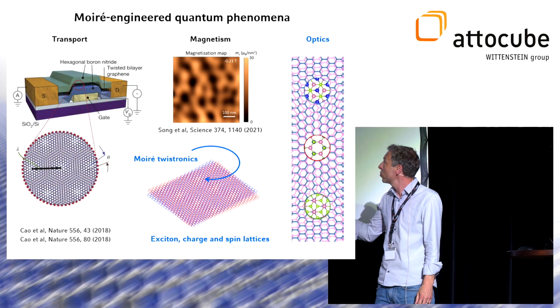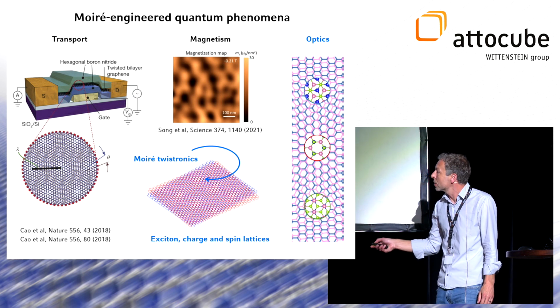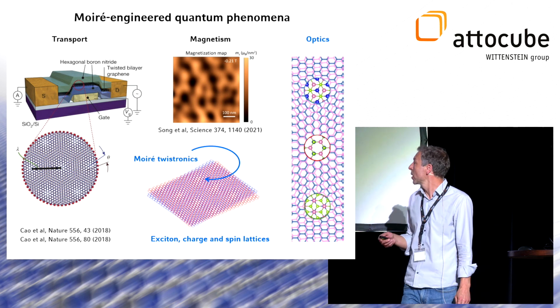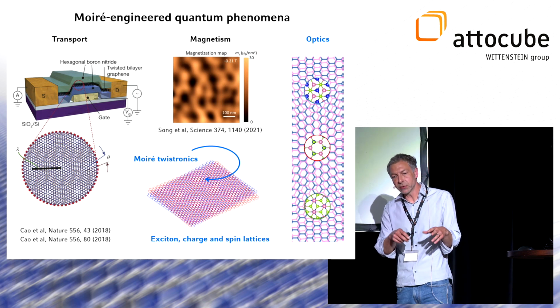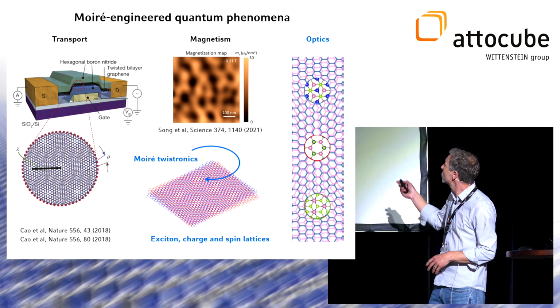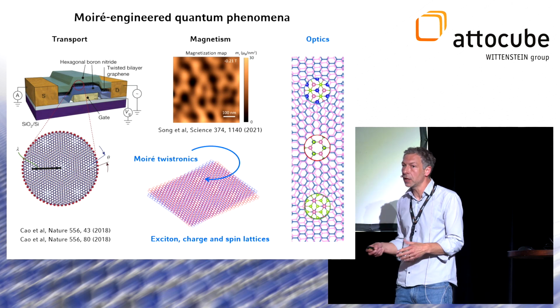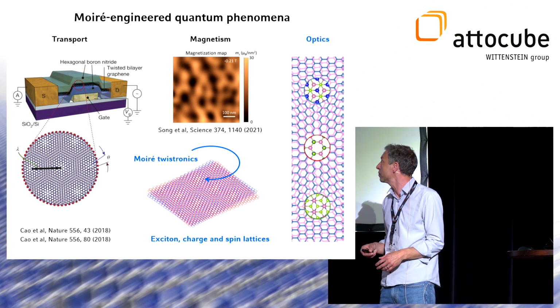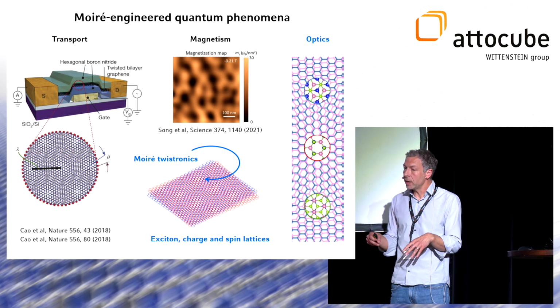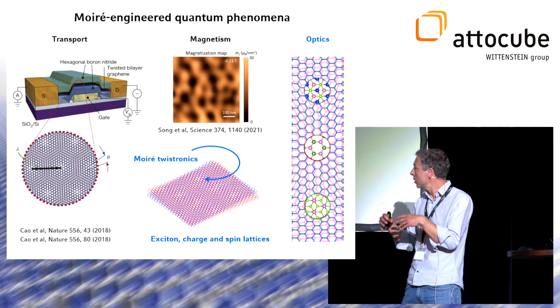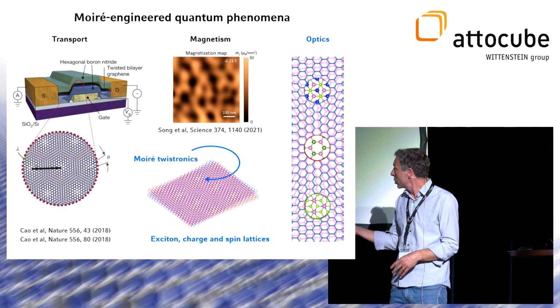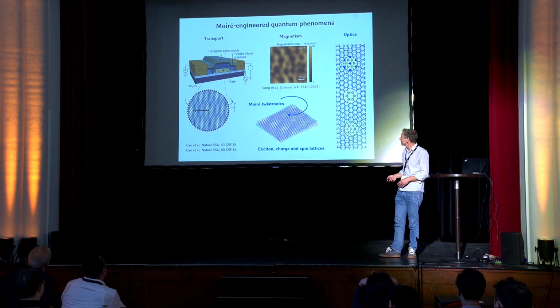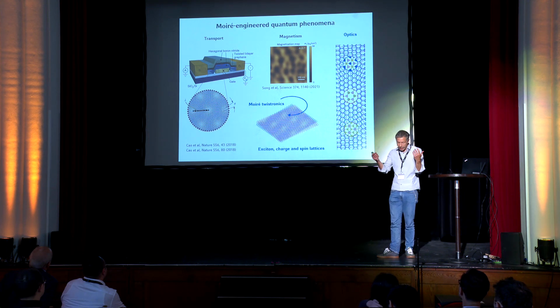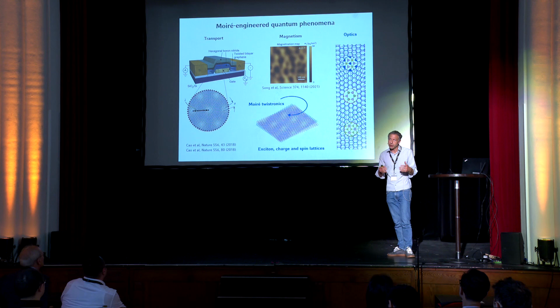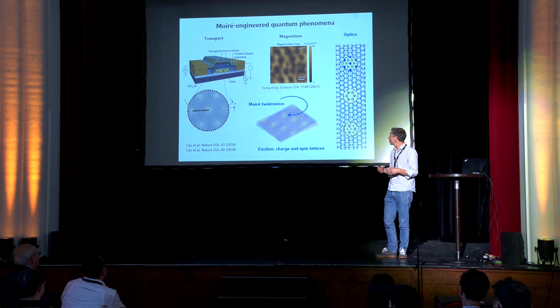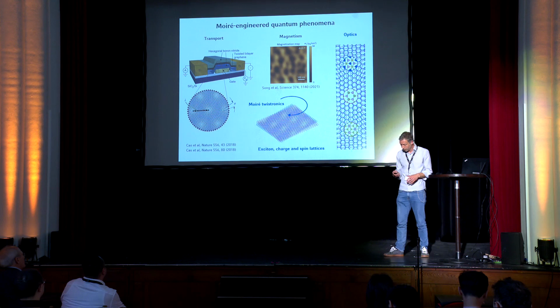Instead, I will focus on moiré twistronics in the context of optical studies involving excitons, where excitons are registry specific. So they pretty much sense the underlying moiré structure or the absence of it. But at the same time, they are sensitive to charge doping as charge is being built up in such a moiré heterostructure, realizing effectively a triangular charge lattice or tagged with a charge spin lattice.